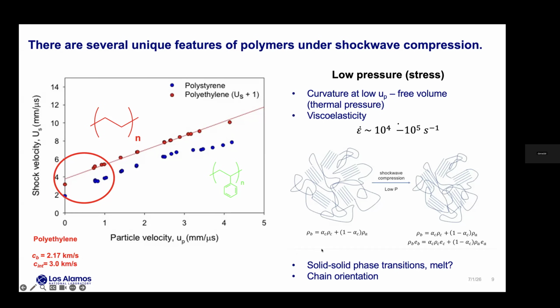And some other things that could happen in this regime is you could drive solid-solid phase transitions. We know that phase transitions for crystalline materials tend to be quite rich at low pressures. With polyethylene, I showed you the melt temperature. There's also the question of, do the crystalline domains melt under shock loading, and can you see evidence of that? Because the expected change in volume associated with melt in polyethylene is on the order of 20%. And then, of course, you might expect there might be some chain orientation or texturing that could take place within these structures.